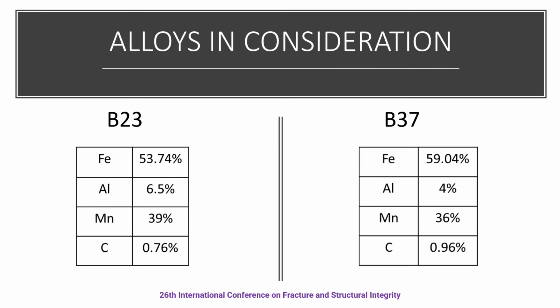Now, the alloys in consideration are two types of alloys which were named B23 and B37. It can be noticed that in B23 the amounts of manganese and aluminium are higher, which is 39% and 6.5% respectively, whereas in B37 the aluminium content is 4% while manganese is 36%.